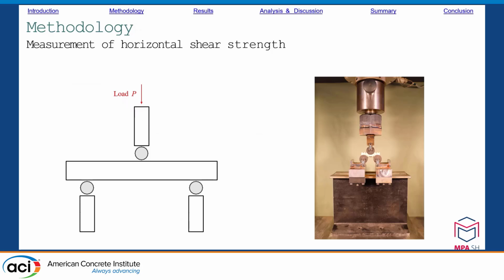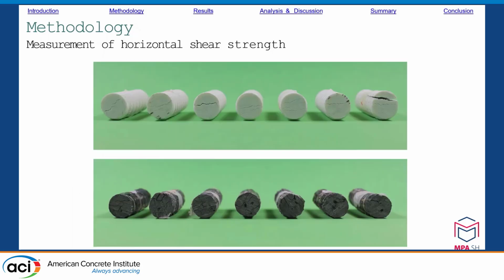The third test carried out was the test to determine the apparent horizontal shear strength. Here, a 3-point bending test was performed at a short span, forcing shear failure in the horizontal direction and parallel to the fibers. The following photos show specimens with a diameter of 60 mm after failure. The parallel cracks at the end of the glass fiber rebars in particular are clearly visible.